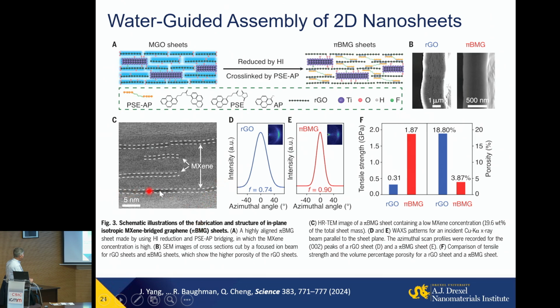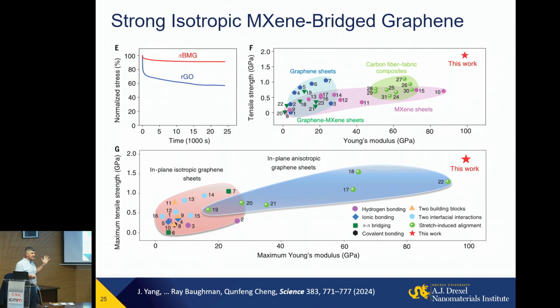This film, you see the same straight MXene flake, remember, has tensile strength close to 2 gigapascal. Again, for people who don't know it, twice the strength of steel, good quality steel, assembled at room temperature from 2D flakes and molecules. It's the future. It's basically something which allows us to take technology to a level which has not been seen before. Moreover, this film is also ionotronic. It conducts ions. They showed this film can work as a supercapacitor efficiently here. And basically, it just goes beyond everything that has been demonstrated mechanically before.